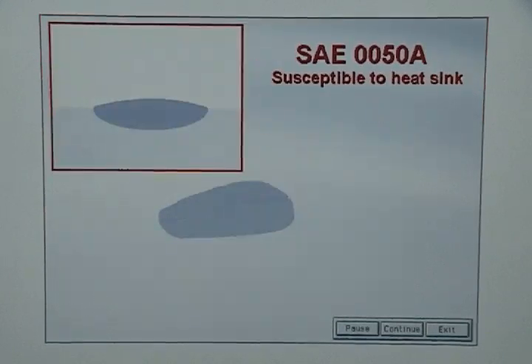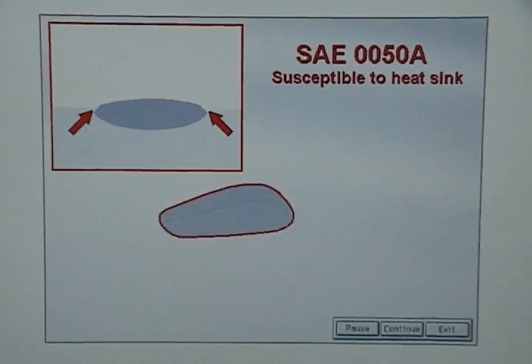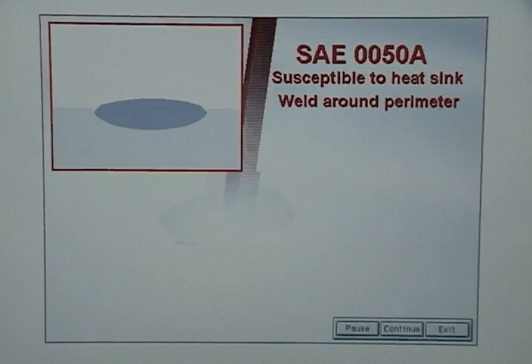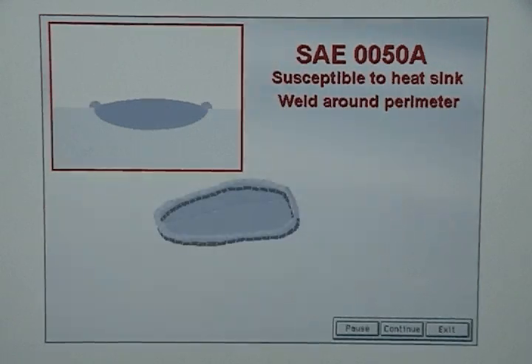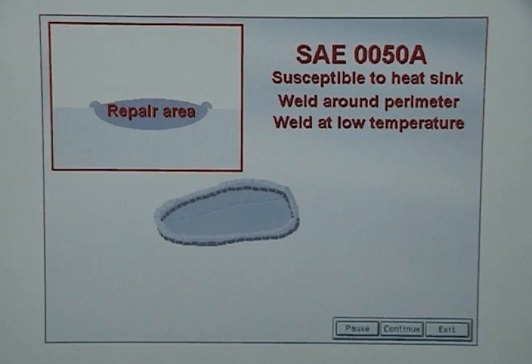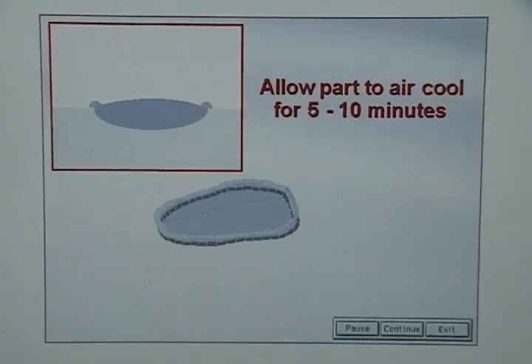Punches made of SAE 0050A are very susceptible to heat sink. Because of this, the place where the repaired area meets the good area will have a small indentation. To remedy this situation, another weld bead will have to be run around the perimeter of the repair weld. This weld bead needs to be applied at a low temperature and will join the repair area to the good area. When the welding is finished, allow the part to air cool 5 to 10 minutes.